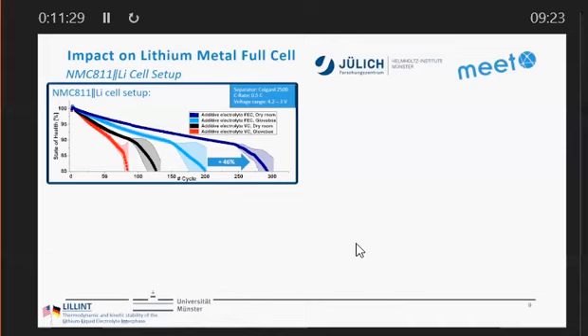In the dry room, it looks like it really helps to do something in the dry room instead of in a glove box. And for FEC, we see an even stronger effect. What was already a better performance in the dry room in symmetric cells is even increased by plus 40% for the system in the dry room. So it's an enormous difference for a full cell, in this case, an NMC811 lithium metal full cell setup.